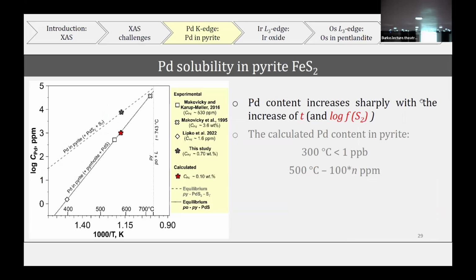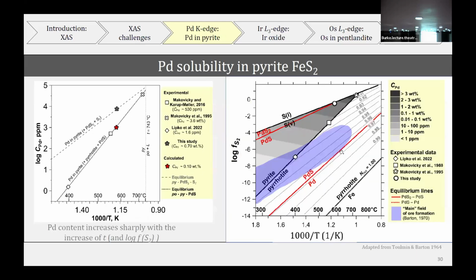Then we tried to make an assessment of the solubility of palladium, and it depends on the temperature and obviously on sulfur fugacity, because we're working with a sulfur saturated system. So they calculated, maybe the major equilibrium in nature is the pyrrhotite equilibrium, and the concentrations vary quite a lot, from ppb to a few hundred ppm level. In nature, as I showed with the natural samples on the first graph, the maximum solubility is a few hundred ppm, and these are few findings. And in our samples, we found up to 0.70 wt%.